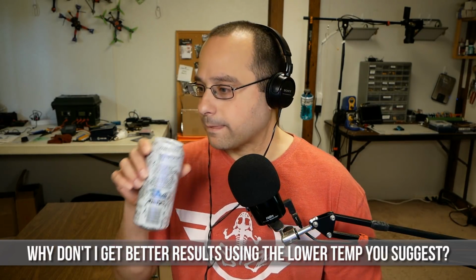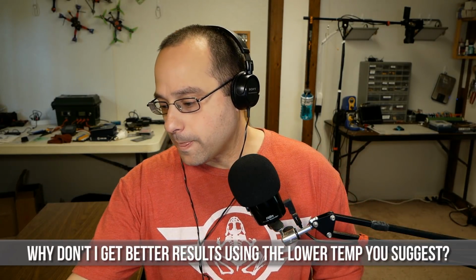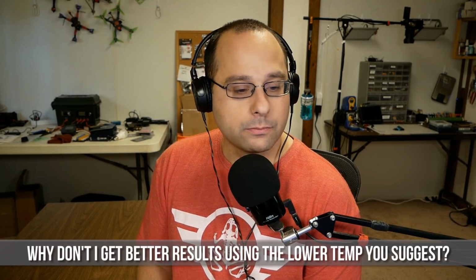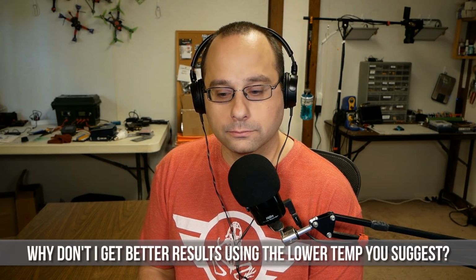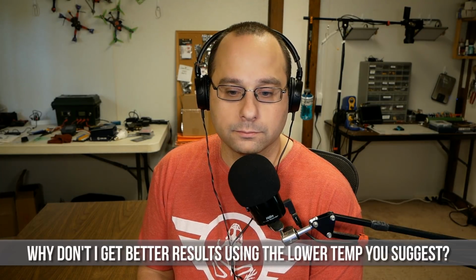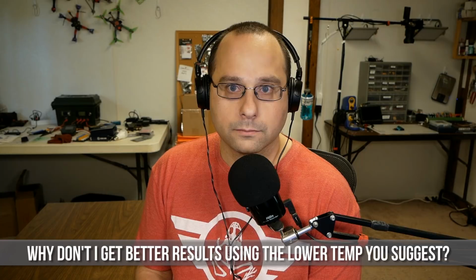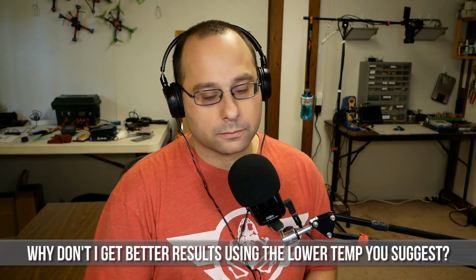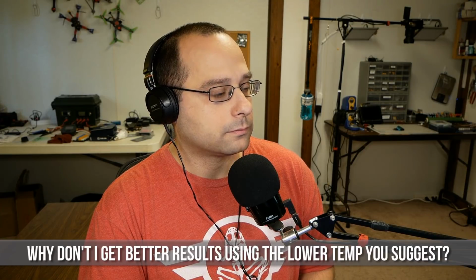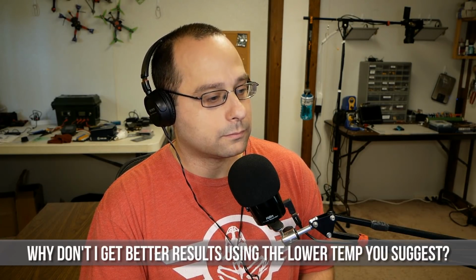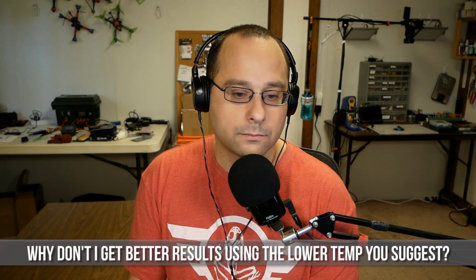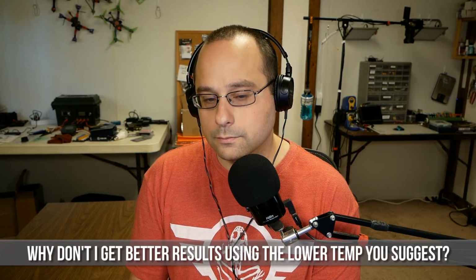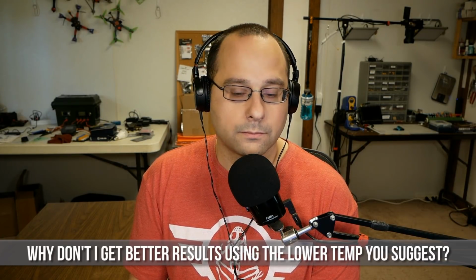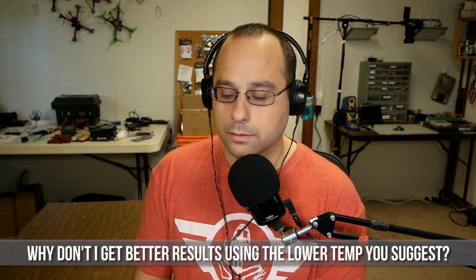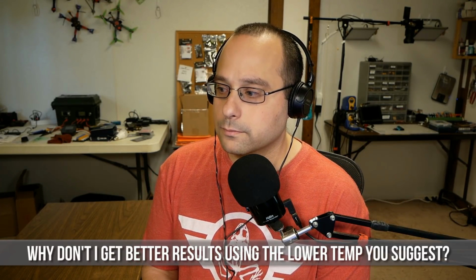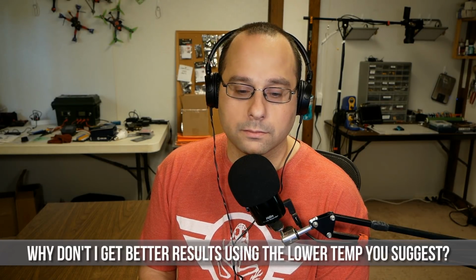That's actually a very good point you bring up, because soldering wires is different than just soldering chips on a board. With chips on a board, you don't have too much to draw heat away from the joint, whereas when you're soldering a wire, that heat is going to start traveling up the wire and absorbing some of the heat you're trying to put on the solder joint. So in the case of wires, it's not a problem to raise the temperature to a higher amount, like 400 C. Depending on how thin they are, maybe 28 or 30 gauge won't need that, but when you get to 22 or 18 gauge, you probably do need a higher iron temperature to get better flow, and faster. So it's really a function of what you're soldering, and the wires will absorb the heat and pull it away from the joint.